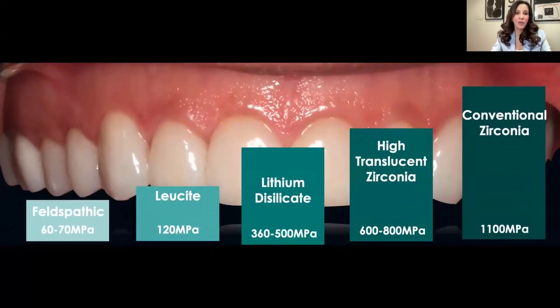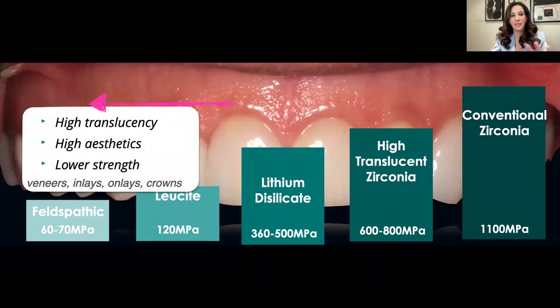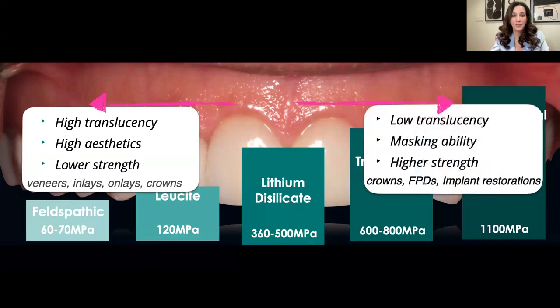And so now that you know the materials that are available, again, in broad strokes, the classifications of dental ceramics, you can appreciate that the materials, the feldspathic, the particle-filled glass, et cetera, have a higher translucency, higher aesthetics, however, lower strength compared to your high translucency zirconia and conventional zirconia, whereas the materials on the right have a lower translucency that has the masking ability to mask any discoloration, and higher strength, and the indication is more widespread for crowns, fixed partial dentures, and implant-based restorations.